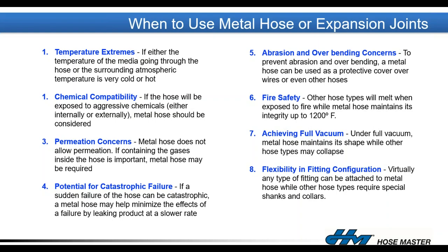Permeation concerns is another reason why metal hoses are used, even if the application requirements really aren't severe, otherwise that would require the use of a metal hose. So if permeation is a concern, meaning you don't want any of that media to permeate through the wall of the hose, which can happen with rubber hoses, Teflon hoses, and composite hoses. Metal hose, for all practical purposes, does not allow that permeation to occur. And if keeping that media inside the hose is important, a metal hose may be required.